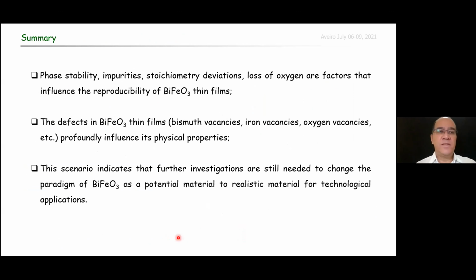So, in summary, we observed that the control of different parameters is essential to the reproducibility of BiFeO3 thin films. On the other hand, the common defects in BFO thin films, such as bismuth vacancies, iron vacancies, and oxygen vacancies, have a profound impact on its physical properties. And finally, the described scenario indicates that additional investigations are still needed to change the paradigm of BiFeO3 as a potential material, a realistic material for technological applications.